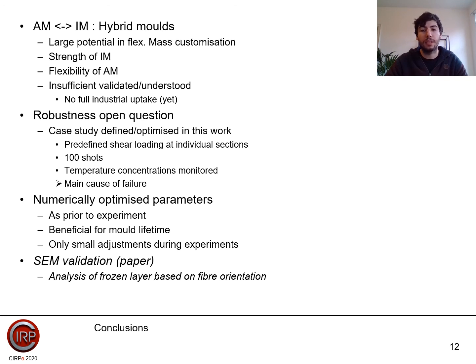An experimental test campaign consisting of 100 shots in combination with this design reveals that in fact temperature concentrations are the main cause of failure, possibly combined with high local stress concentrations inside the mold due to large temperature variations. Using numerically optimized parameters as a prior setting, the lifetime of the mold in digital ABS was higher than predicted. Yet, the parameters required small adjustments during the experiments to achieve the final product.